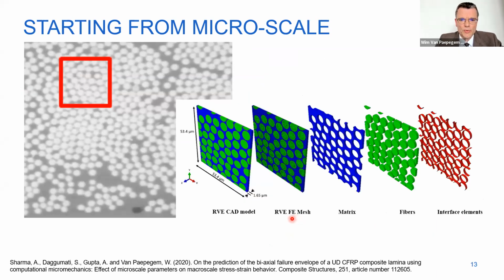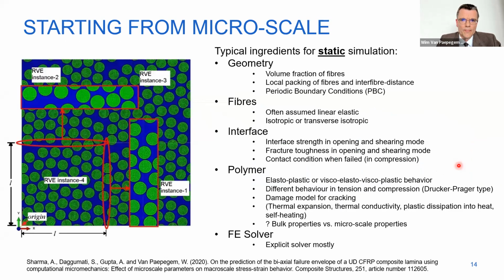And now zooming in a bit on the ingredients. So we have a CAD model, for example, then we mesh it. We have a polymer matrix mesh, we have fibers modeled, and we have this interface. Typically, we explicitly model it, either with cohesive elements or cohesive behavior, to also have this interfacial debonding made possible. And we do need already quite some ingredients if you look to just a starting simulation.